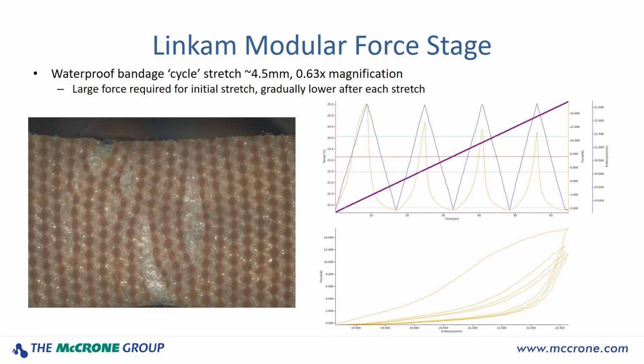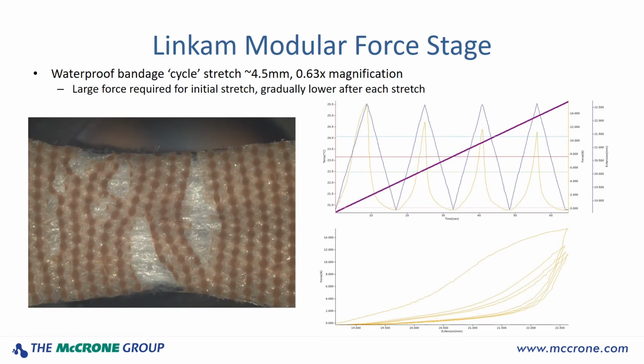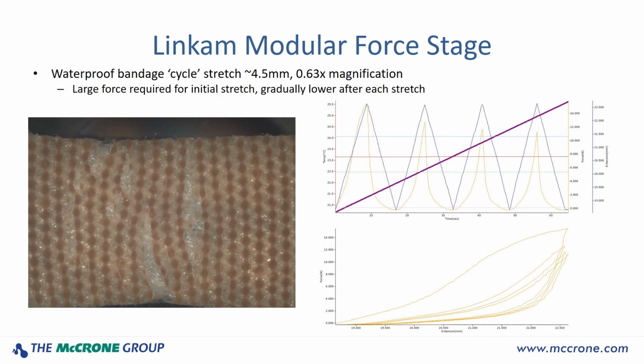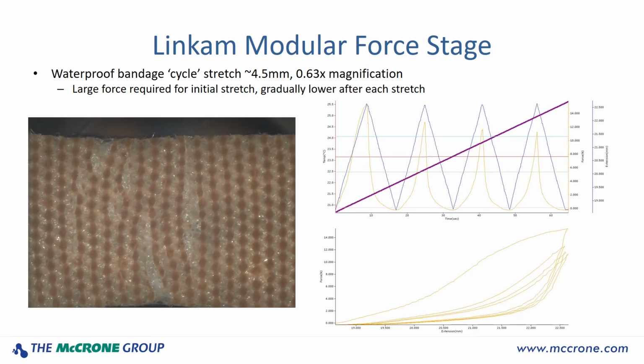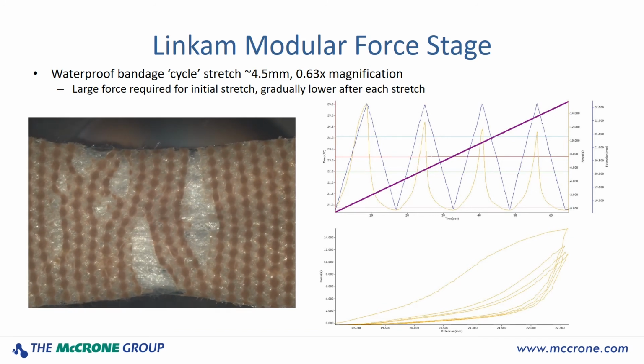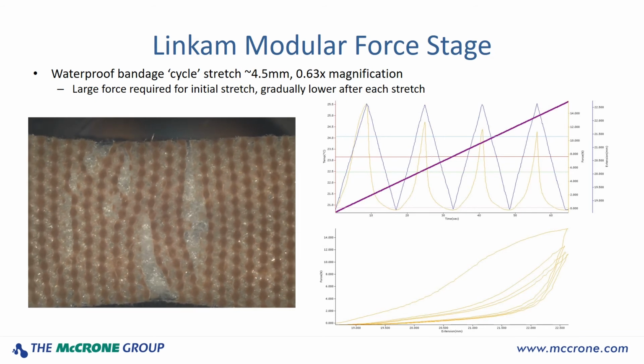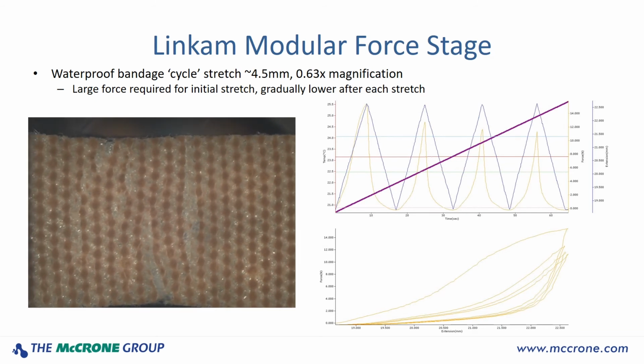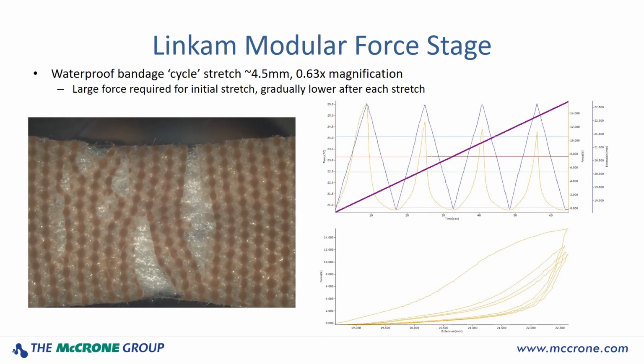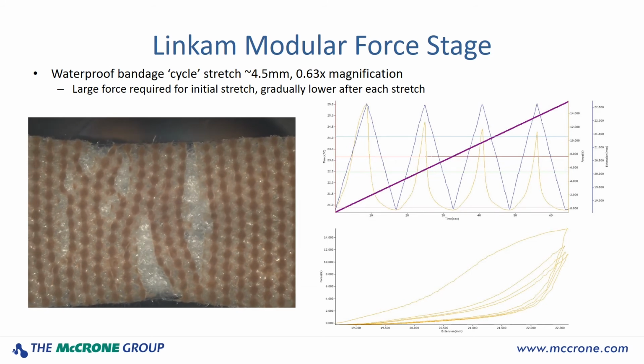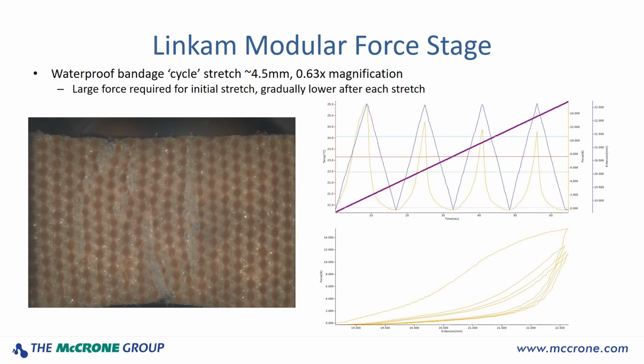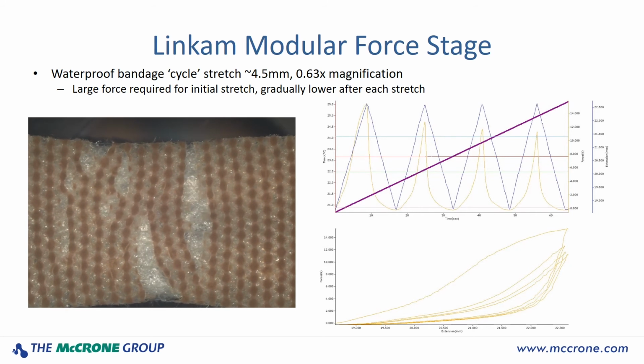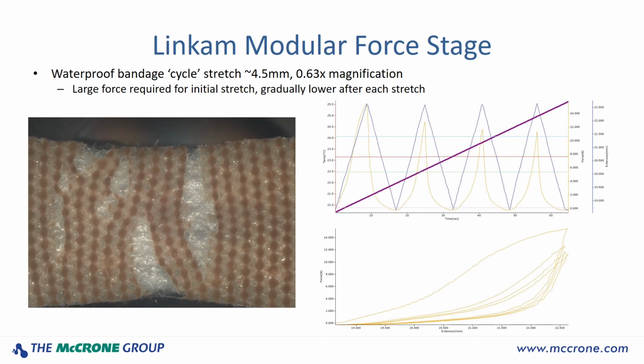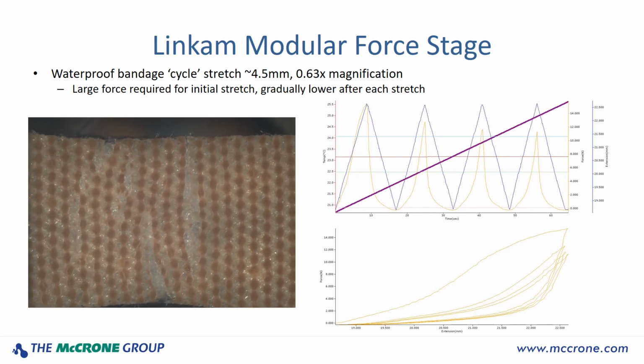The second test for the waterproof bandage was similar to the first, utilizing a cycle stretch, except this time going a bit further to roughly 4.5 millimeters. I noticed a large force required for the initial stretch, and then the stretches afterwards required less and less force, indicating that elasticity of the bandage was not maintained as well as in the first cycle test.